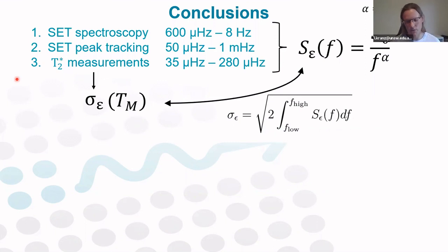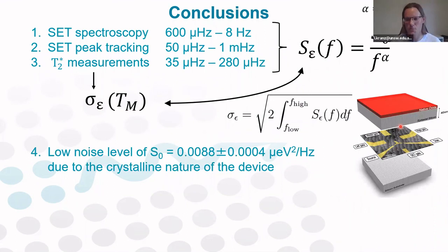So up to now, for electron spin qubits, people would either report the noise that's coupling to the charge sensor or the noise that's coupling to the double dot detuning. But we showed that, at least in our device, this relationship is well described by this beautifully simple integral. And the fact that we have overall low noise in our device, we attribute to the crystalline environment hosting the qubits and the fact that we're separated from the interface with oxide.